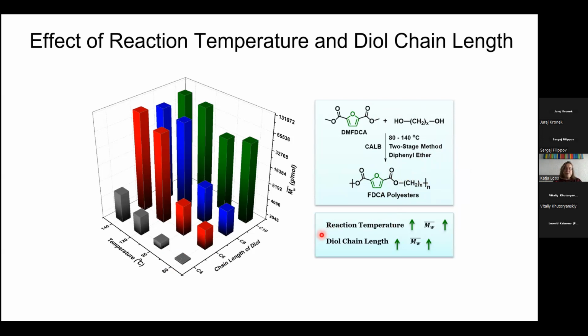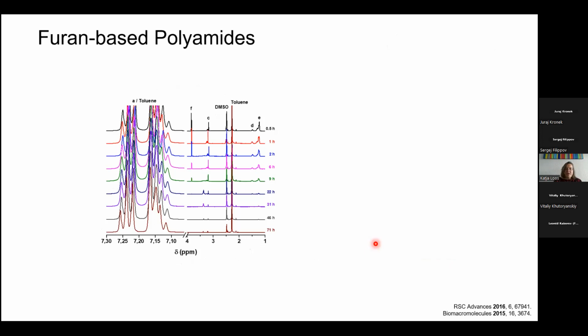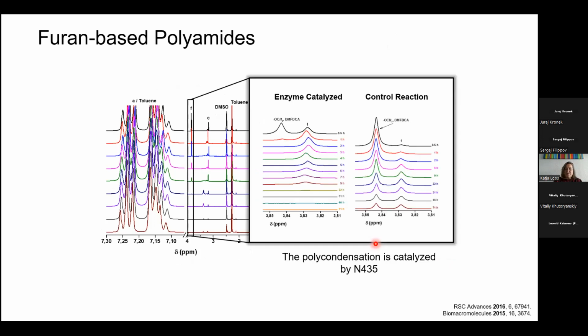But we by now also learned that with higher reaction times, we get higher molecular weights. And if the diol chain length gets higher, we get higher molecular weights. But at a certain point, it also goes down again. And we have a lot of ways to tune this polymerization. And we also know a lot about these polyamides. And here again, I can show you that in the polyamide case, there's an underlying chemical reaction, because polyamides are faster to be synthesized than polyesters, but it's really catalyzed by the enzyme, and it's not just appearing and the enzyme is there.